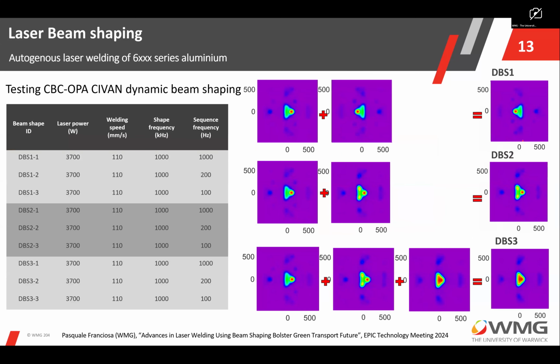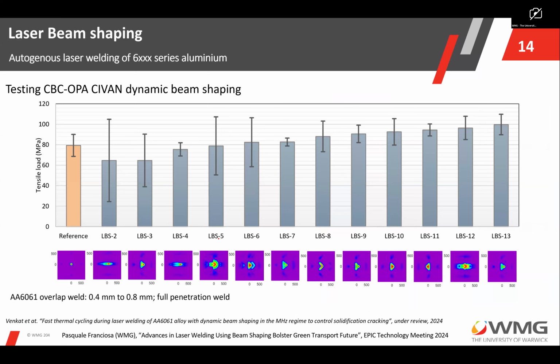And then we also tested something more dynamic. And you can see some of the frequencies we have been using. And those are some of the results now. So those are the tensile load in megapascal for those shapes. So now if you compare the baseline on the left-hand side, close to 80 megapascal, and then you see how much improvement you can get by changing the shape.